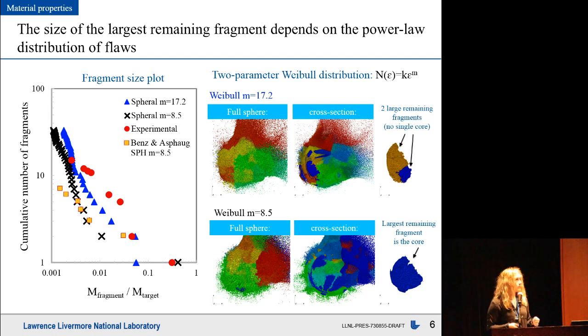When we put M equals 17.2 into spheral, we found that we're actually able to match the smaller fragment masses much better to the experimental trend line, but not so much the larger fragment masses, where 17.2 are the blue triangles.